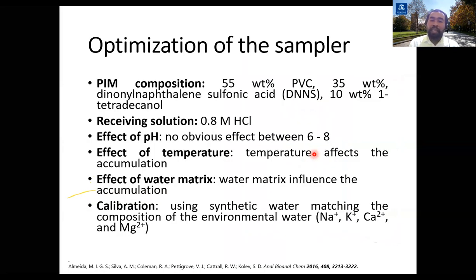Again, there have been a number of parameters optimized, including PIM composition as shown here, receiving solution, and the effect of pH, where they found no obvious effect, which means that the accumulation of ammonia is similar across the normal pH of our water system, which is between 6 and 8. They found that temperature affects the accumulation, and that's why they have to perform the calibration at different temperatures to compensate for the effect of temperature. They also studied the water matrix effect using source solutions of not only soft water, but hard water and very hard water as well, because that's what is normally encountered in the environment.